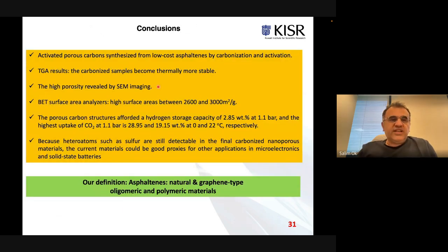Let me come to my conclusions. First of all, activated porous carbons were synthesized from low-cost asphaltenes by carbonization activation pretty successfully. TGA results showed the carbonized samples become thermally more stable compared to raw asphaltenes. We can see the high porosity of carbonized asphaltenes by SEM imaging and also by BET surface area analysis, with surface areas between 2,600 and 3,000 meters square per gram.